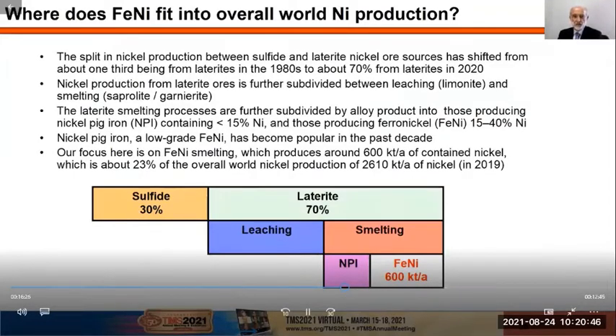The split in nickel production between sulfide and laterite nickel ore sources has shifted from about 1/3 being from laterites in the 1980s to about 70% from laterites in 2020, shown in the figure below. Nickel production from laterite ores is further subdivided between leaching of limonite and smelting of saprolite garnierite. The laterite smelting processes are further subdivided by alloy product into those containing nickel pig iron, containing, say, less than 15% nickel, and those producing ferronickel itself, ranging from 15 to about 40% nickel. Nickel pig iron, basically a low-grade ferronickel, has become popular only in the past decade.